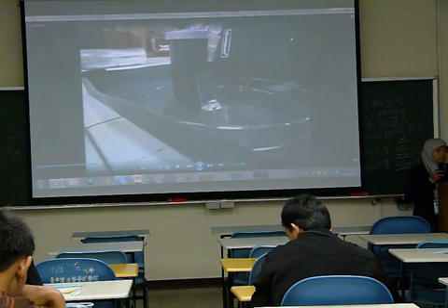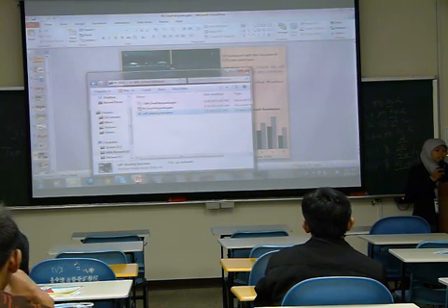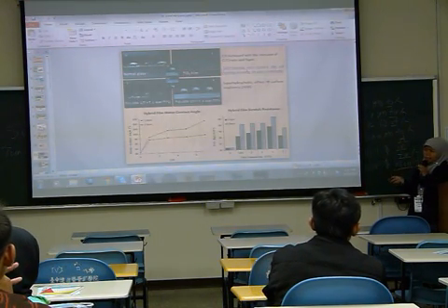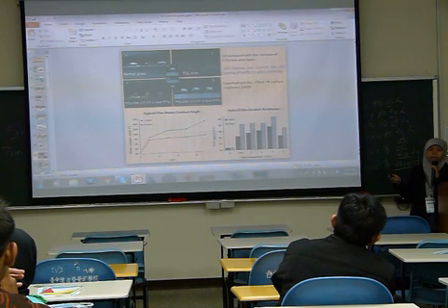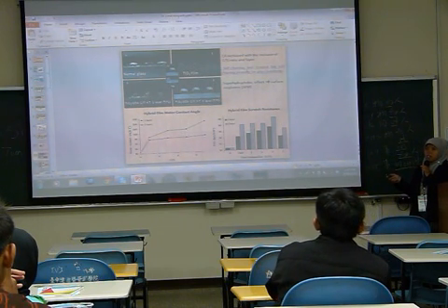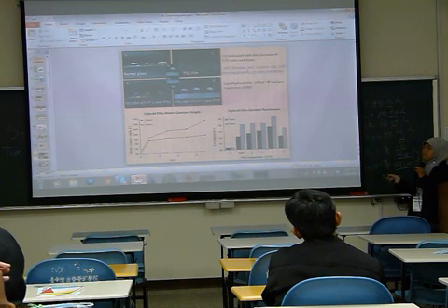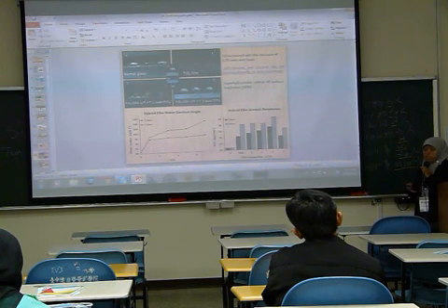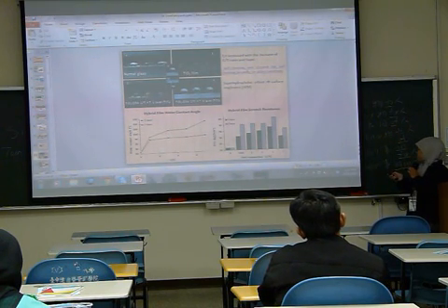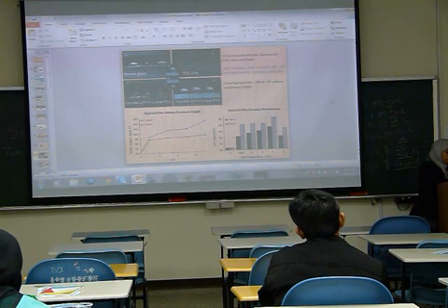This is the proof. We can prove by this video that all of the hybrid film glass has the self-cleaning property. And since the chemical nature of all the hybrid films was the same, it was proposed that this self-cleaning phenomenon was the responsibility of the surface roughness, as we can see in this AFM image.